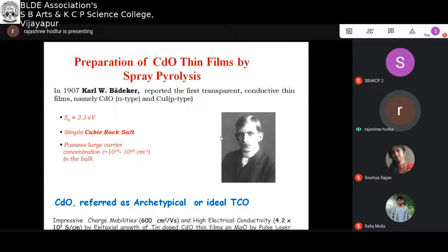So apart from the tin oxide, as I told you all, a lot of recent work is mainly focused on heavily doped metal oxide semiconductors since they exhibit plasmonic properties. So another important metal oxide is cadmium oxide. Using our home built spray pyrolysis setup, we were able to make cadmium oxide thin films. In this TCO category, it was cadmium oxide which was first discovered by Carl Badeker. Its band gap is around 2.3 electron volt, it crystallizes into cubic rock salt, and it possesses a very high carrier concentration, which is of the order of 10^18 to 10^20 electrons per centimeter cube in bulk form.